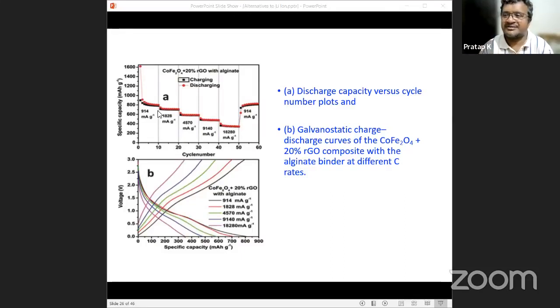Generally, I think everybody knows it, you who are using electric vehicles. They say slow charging, so you should leave the vehicle overnight and it gets charged. Or there is also the option for fast charging, so you can choose the fast charging option. Then they will warn you that after one fast charging, you have to do at least 5 or 6 slow charging. Otherwise, the anode materials and cathode materials within the battery get pulverized and the capacity will drastically decrease. So here, our material exhibited very good stability towards changing current. Even though we changed the current, the material did not get damaged and retained its capacity.